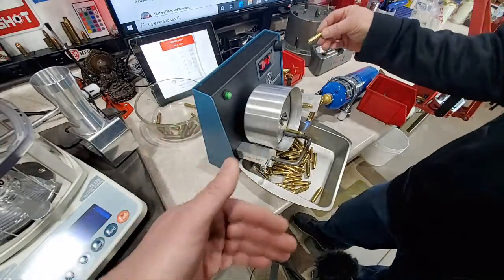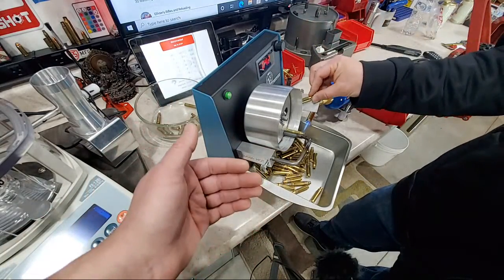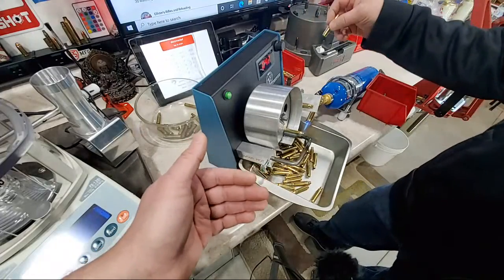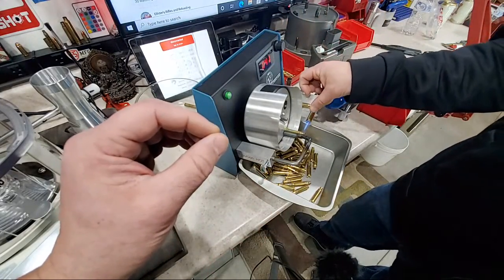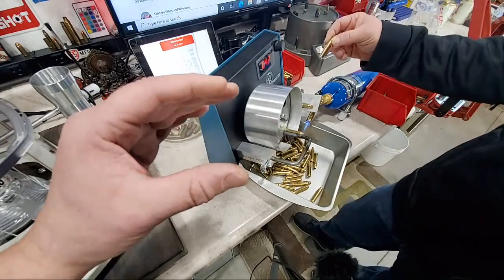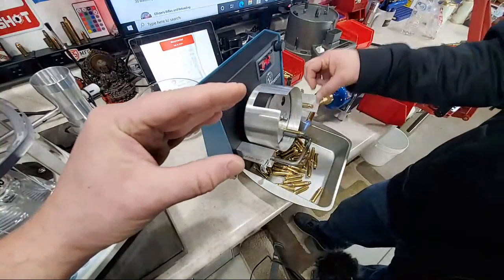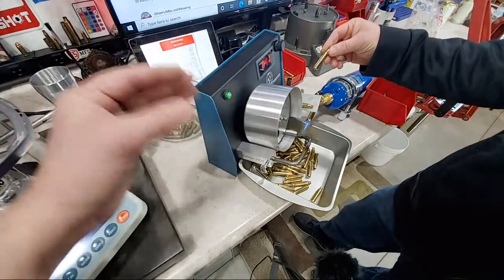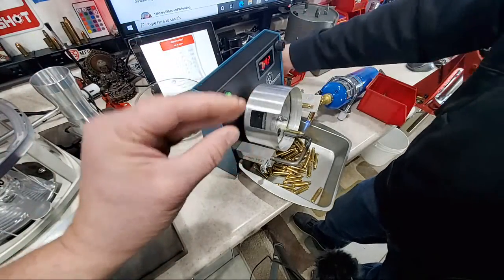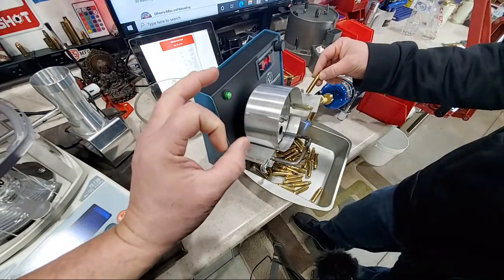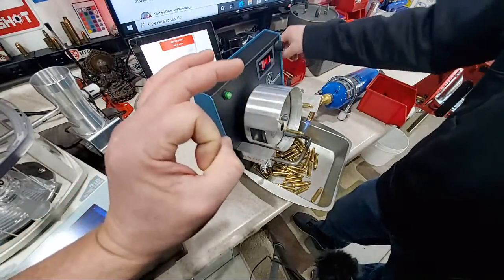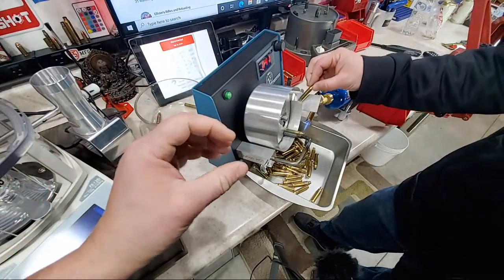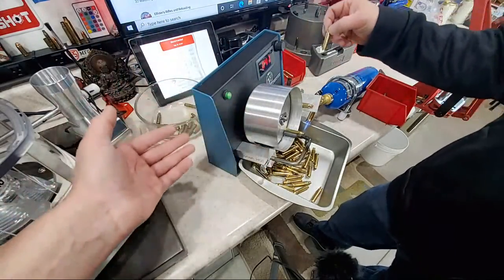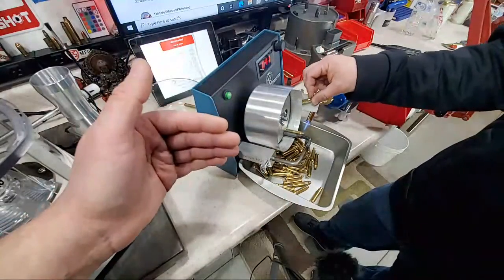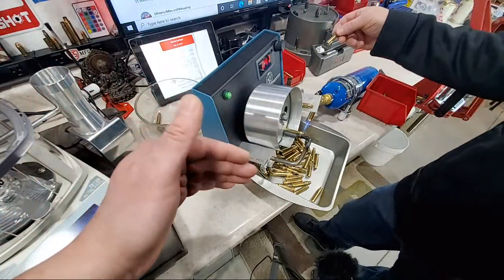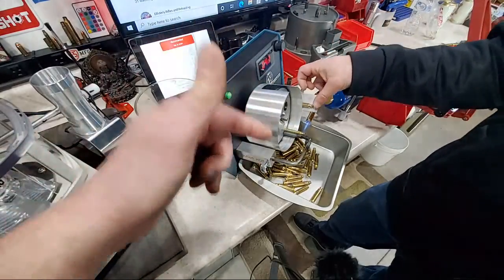And some of you guys might be questioning, if you're actually new to the game, why do we anneal? We anneal for a couple reasons. When you fire that round in the chamber, the brass expands. In this case, it's expanding 0.007 of an inch. And then it jacks out, and then we bump that brass back down 0.004 of an inch, and we put the body back into spec, the neck back into spec, we bump back the head space, and then we do that over and over. We reload it, we fire it, we reload it, we fire it, and that's called work hardening the brass, and it makes the brass brittle. And that's why you should be annealing.